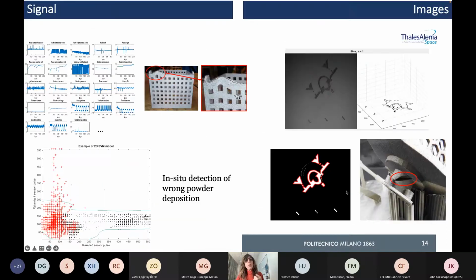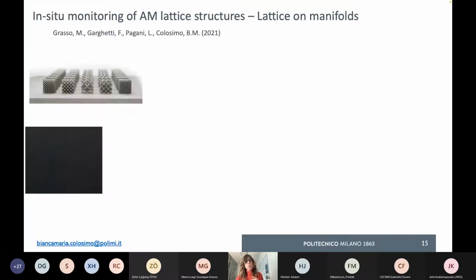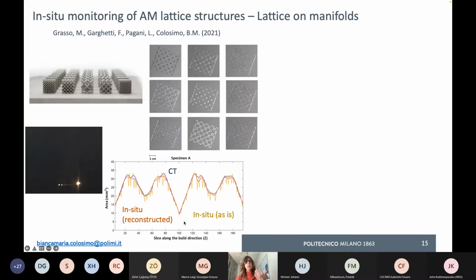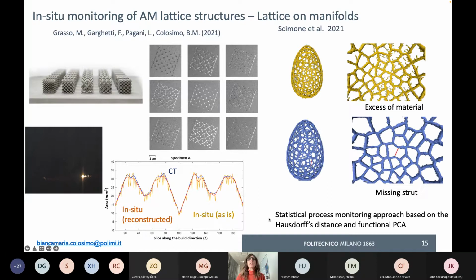And we can clearly move ahead and think about this concept even for very complex shapes like lattice structures. We have been showing that you can in situ reconstruct the geometry of a lattice structure that is quite complex to be reconstructed, having some sort of in situ reconstruction that is quite consistent with respect to what you can see ex situ, thanks to the X-ray CT, again, layer-wise. And you can even think about a new dimension in which this voxel-like picture is no more about pixels, you are moving to a 3D shape. You can even use a similar concept to detect if something is wrong in complex shapes, so basic lattice or manifold or something like that. You can develop some specific tools for doing this job as well.